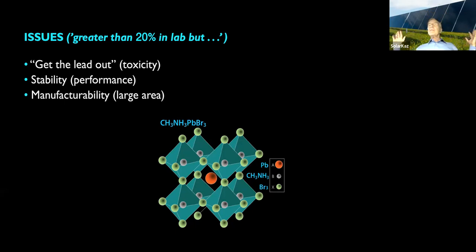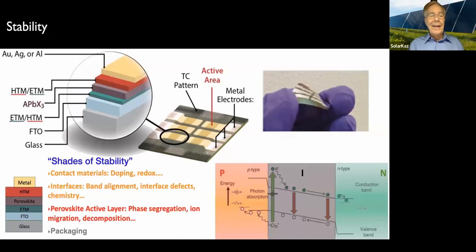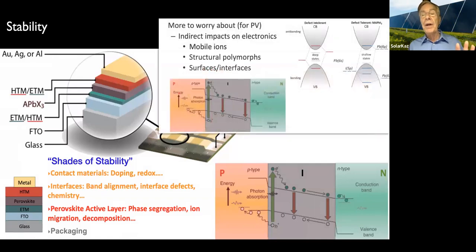You have a crystalline silicon module out there, you have light-induced degradation that you see. During the first, for instance, if you look at the warranty from the people who make these, in the first 2 years, they built in the fact that the degradation is part of their warranty, long-term warranty, that usually about 0.5% a year. During the first year, it might be 1 to 1.5% because of light-induced effects. Every technology has this, but it stabilizes. So let's see here. Let me show these things. I want to point out that there are many shades of stability, the contacts, the interfaces, the material itself, and these are all being investigated. Okay, very, very carefully on this.